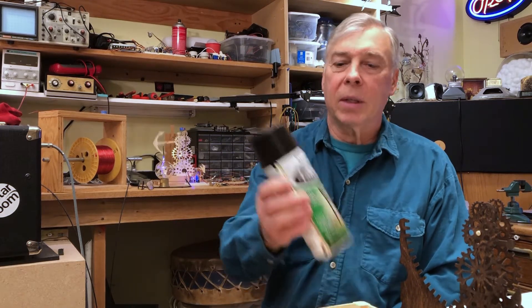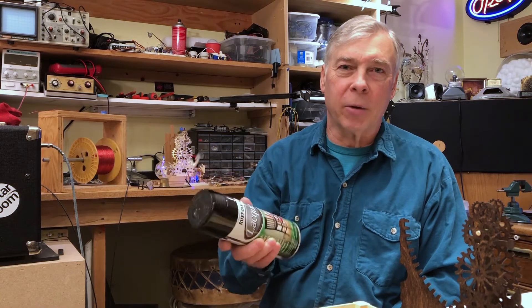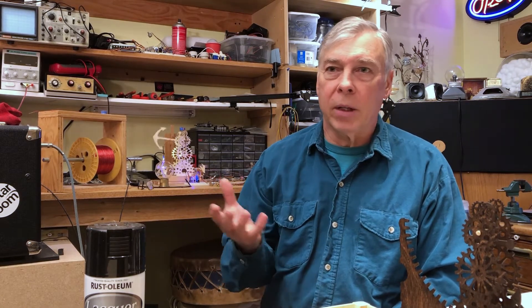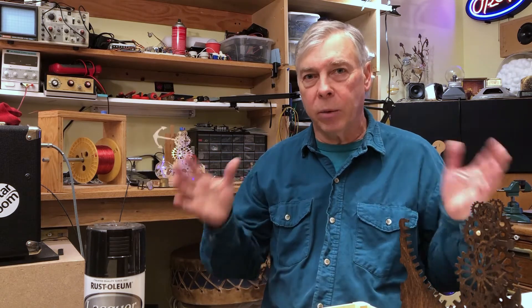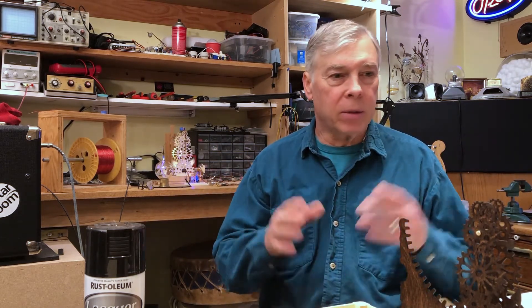Until I found a post on Reddit that said to use lacquer paint. You have to use lacquer paint for these blue laser diode engravers. Other paints would seem like they engraved, but they just never got down to the bare metal. There's usually a residue after the laser has done its thing, and you've got to be able to clean that residue away without disturbing the rest of your painted surface. I kept running up against that — I was scrubbing too aggressively and the other paint would get attacked, messing up the design.